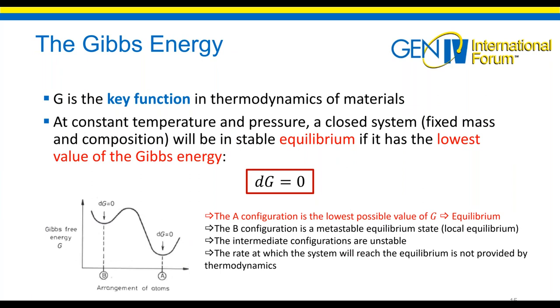In fact, at constant temperature and pressure, a closed system will be in stable equilibrium if it has the lowest value of the Gibbs energy. And in this point, we have the derivative of G that is zero. But as we can see here on this diagram, it's possible that sometimes you have different equilibrium states where the derivative of G is zero, but only one will be at the lowest value. And this one, so A, is the lowest possible value of G. So this is the stable equilibrium. Whereas B is what we call a metastable equilibrium state, because the derivative of G is zero, but it's not the lowest possible value of G.